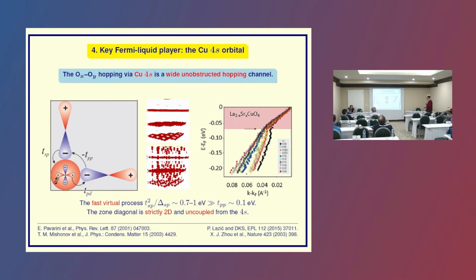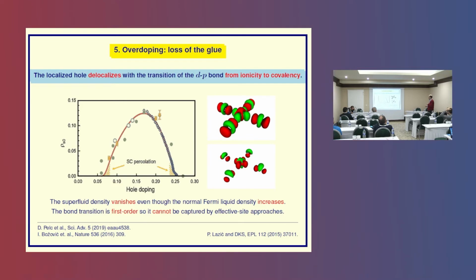In the underdoped regime, the dp bond is ionic, and you have a localized hole. This is the CuO4 ion molecule. And on the overdoped side, it becomes covalent, which means you have a Fermi liquid, but this Fermi liquid does not superconduct because, as Neven has pointed out, this localized hole is important for the glue. Okay, so you have a lot of Fermi liquid spectral strength coming in, but the superconducting strength is coming down.